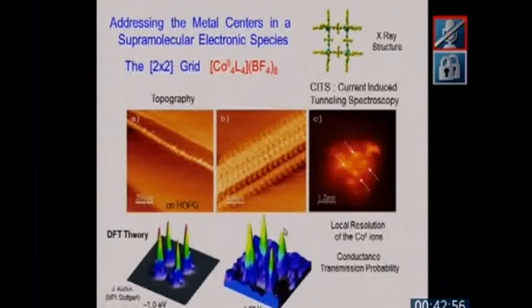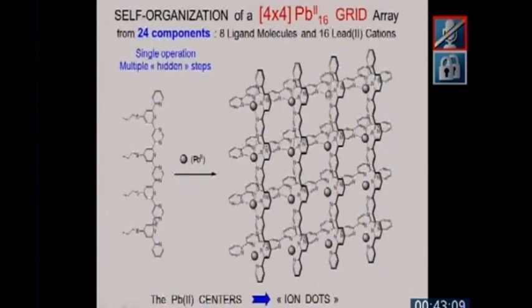Let's just look at the most complex, the largest of these grid entities we have been making, taking this ligand, which has 1, 2, 3, 4 subunits, treating it with lead. One assembles in one step this very complex grid of 4 times 4 type, where 4 vertical ligands and 4 horizontal ligands are held together by 16 lead atoms. Of course, this occurs in a single operation, but there are multiple steps behind until you end up generating only this structure. The interest of this structure is not just that it is a complicated structure with 24 components getting together in an organized fashion,